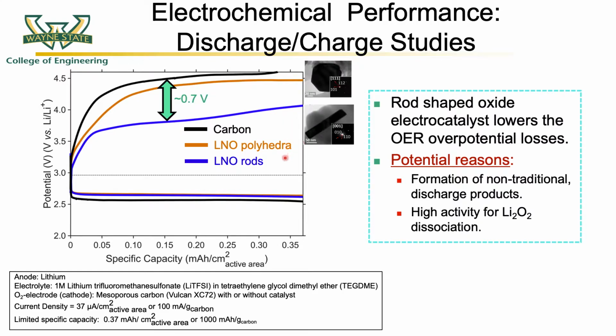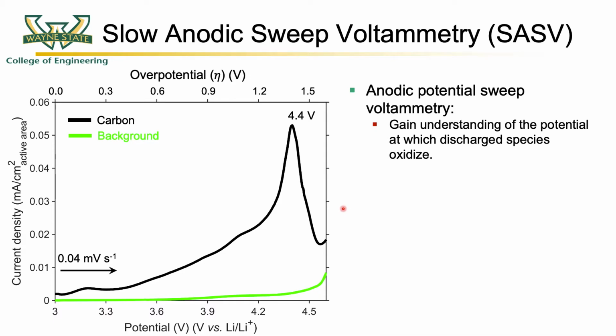oxidize at lower potentials during the charge cycle. On the other hand, it could also stem from the high activity of rod-shaped La2NiO4 structures towards Li2O2 dissociation, leading to lowering of the overpotential losses. To further gain more electrochemical insights, we turn our attention to slow anodic sweep voltammetry during the charge cycle.